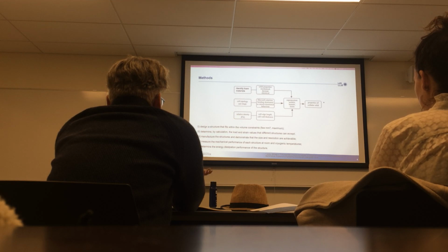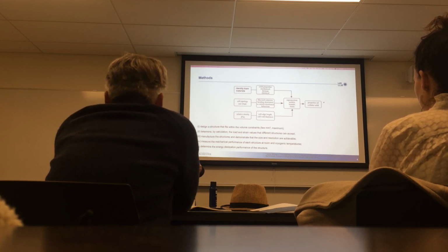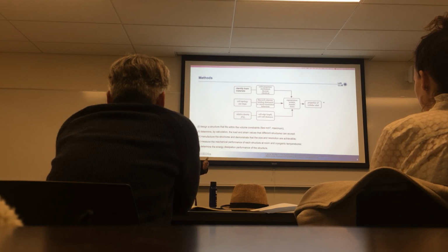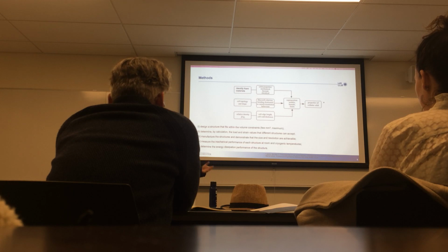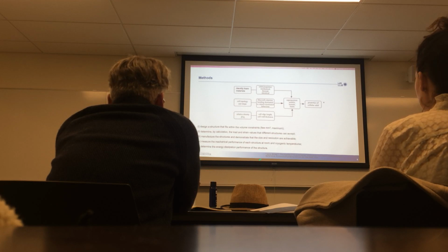The first one, we will design the structure in certain areas. The certain area is 1 cubic millimeter, and then we will use calculation to determine the structure's load and strain values. And the third part is the most important part. We will manufacture these structures and demonstrate the size and the resolution achievable. After we get the physical sample, we will test these structures' mechanical performance at room temperature and cryogenic temperatures. Then we will choose the best performing structures. After we choose them, we will determine the best energy dissipation performance for these structures.